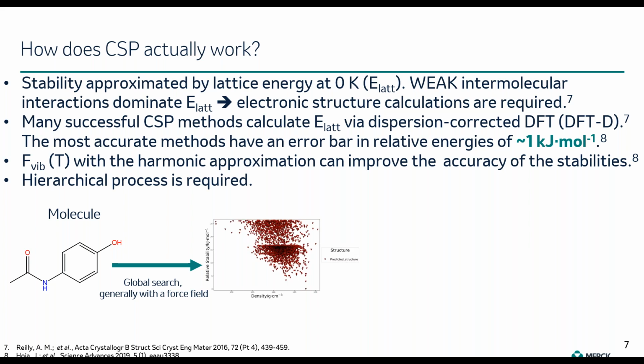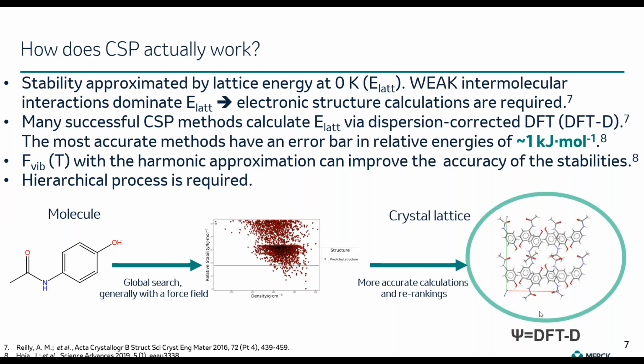And this force field can either be transferable or tailor-made for a given molecule. Only then a cutoff in energy is applied, and the crystal structures that are lower than this cutoff in force field energies are taken forward, and more accurate calculation and re-ranking are performed, and in this case, electronic structural calculation methods are employed, calculating the wave function for the crystal structure.